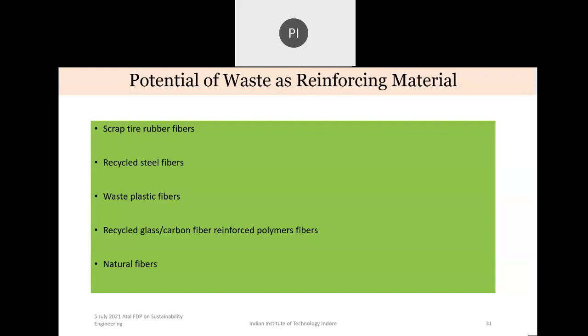Steel reinforcement has a different purpose, and steel reinforcement improves the flexural strength of the structural component, whereas these reinforcements, they don't improve. They might improve, but we should not use them for improving the flexural strength of the member. And this is a mistake which many times people make when they use fibers in concrete. They try to look for improvement in the flexural strength. It may improve the flexural strength, but its primary purpose is to arrest the cracks. And then, of course, you can use recycled glass or carbon fiber reinforced polymers and natural fibers.